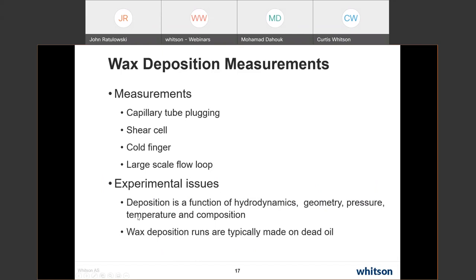Again, deposition is a function of hydrodynamics, geometry, pressure, temperature, and composition. That's why the large scale flow loops are most representative. And wax deposition runs are typically made on dead oil, but that's okay. The only thing you'll see with live oil is a depression of deposition rates and also wax appearance temperatures.